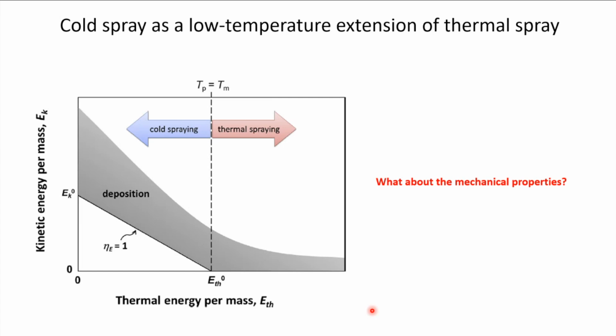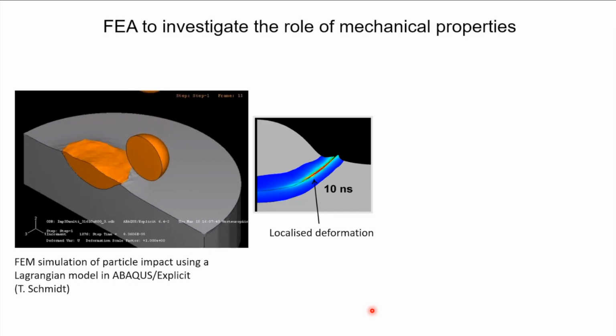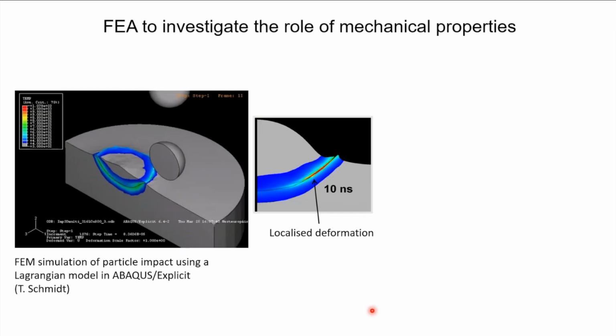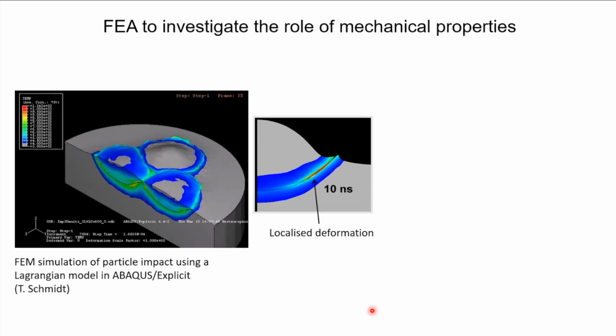Because the experience was that harder particles have a bigger problem in order to stick to the substrate. So that actually drove me into using finite elements. We used finite element simulation in order to study the interface of two impinging bodies. Looking at the interface, we realized that in some regions of the interface, you have localized deformation during a very short period of time.